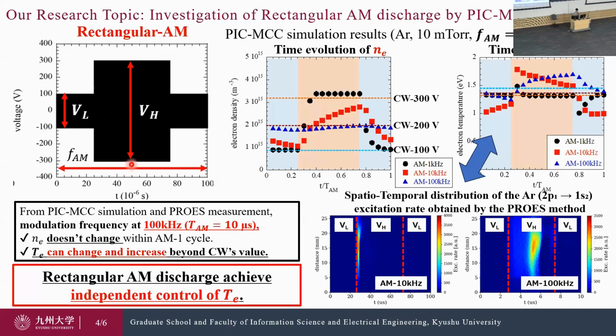In this study, we applied a rectangular AM waveform instead of sinusoidal type modulation to 10 mTorr argon plasma and varied the modulation frequency from 1 kHz to 100 kHz. Here we show the time variation of electron density and electron temperature within one modulation cycle at each modulation frequency, as calculated by the PIC-MCC simulation. Specifically, the horizontal axis represents 1 millisecond for a modulation frequency of 1 kHz and 10 microseconds for 100 kHz.